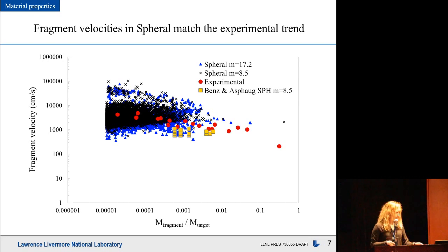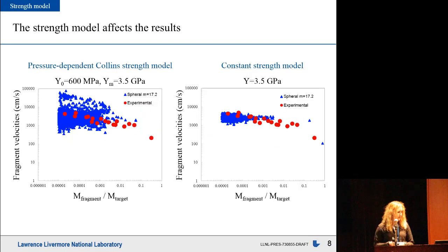So we probed the strength models and found that the strength models do affect our simulation results. When using the pressure-dependent Collins strength model, we find that we get this broad range of velocities for our smaller fragment masses.